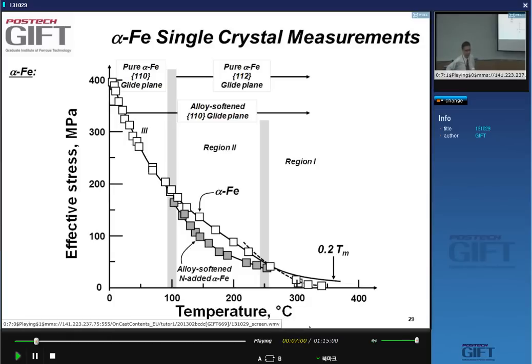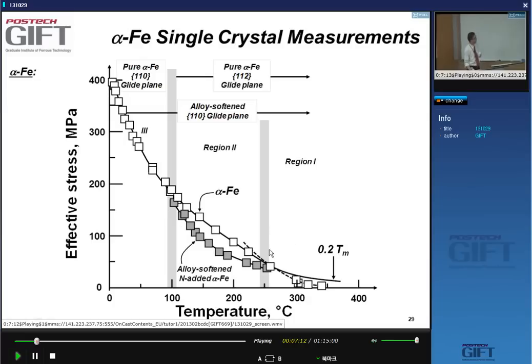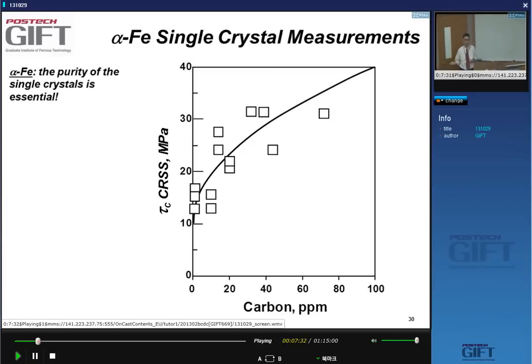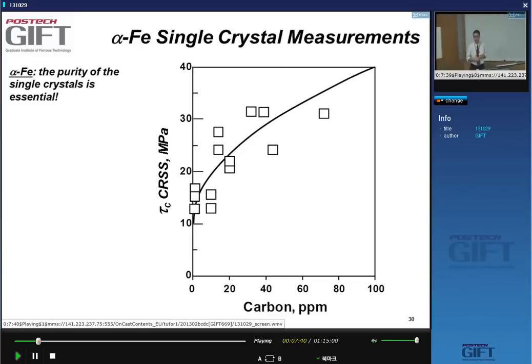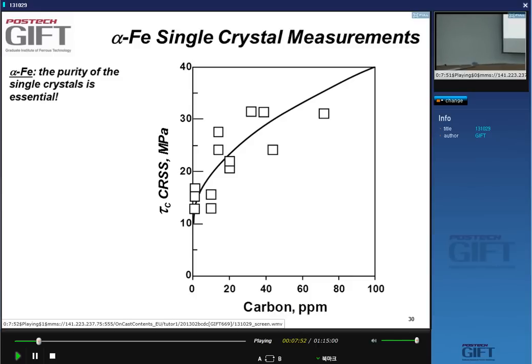There are complications with the slip plane. In pure alpha iron, the slip plane is 110 only at very low temperatures, but in steels, because of alloying, this low-temperature slip system actually prevails also at high temperatures. So in steels, we're probably always looking at 110 slip, but this has been surprisingly little studied. Very few people have done good work on binary alloys of iron to look at slip systems there, partly because it's very hard to make high-purity iron without carbon or other impurities.